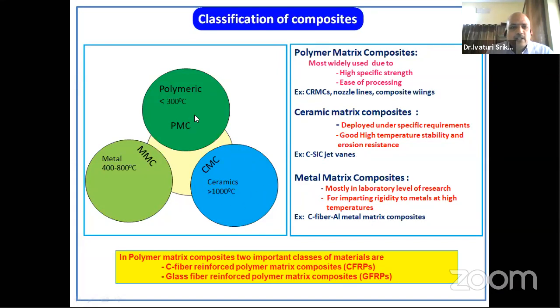So again, depending on the temperature of application, we have to choose what kind of binder we have to go for. Polymeric matrix composites are generally used for low temperatures, generally 150 to 200. There are special polymers which can go up to 300 degrees centigrade also. If the temperature applications are higher, 1000, 2000, 2500, then you have to go for ceramic matrix composites. Metal matrix composites are still in the very initial stage. They have not found many applications except a few research interests that we will not discuss much. So again, in polymer matrix composites, there are 2 important classes of materials. One is the carbon fiber reinforced, the other one is the glass fiber reinforced composites.